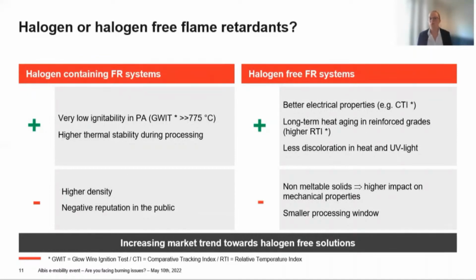However, at the same time, with halogen-free flame retardant systems, you also get some disadvantages, like higher impact on mechanical properties and a smaller processing window. In comparison to that, halogen-containing flame retardant systems show very good performance when it comes to the glow wire index and a very low ignitability, especially in polyamide, and a higher thermal stability during processing, which means that you have a bigger processing window. At the same time, halogen-containing flame retardant systems show higher density and a negative reputation in the public, mainly due to the use of antimony trioxide as a synergist.